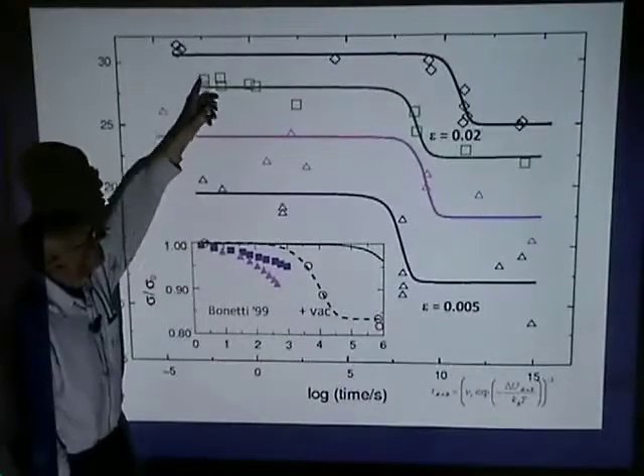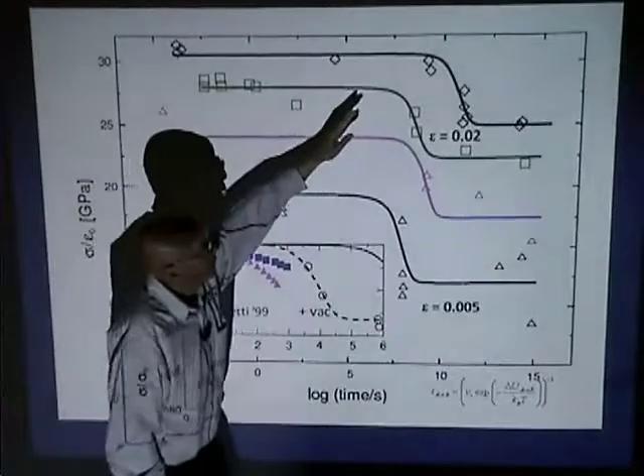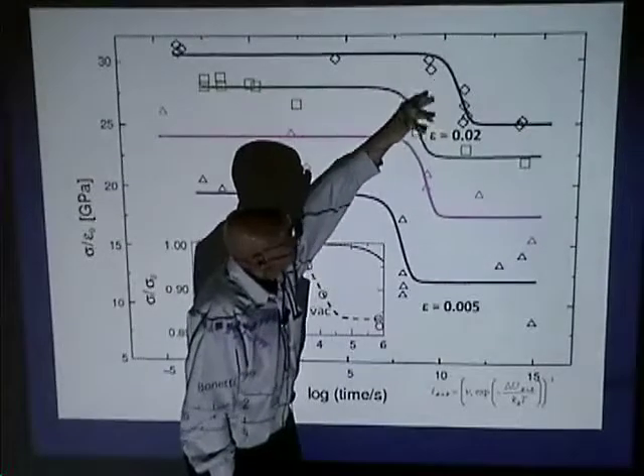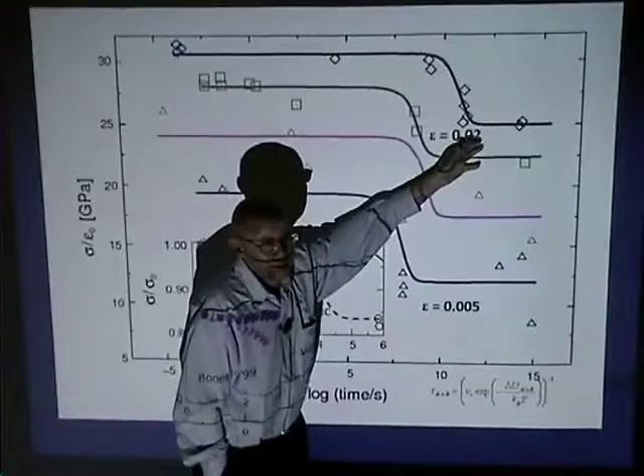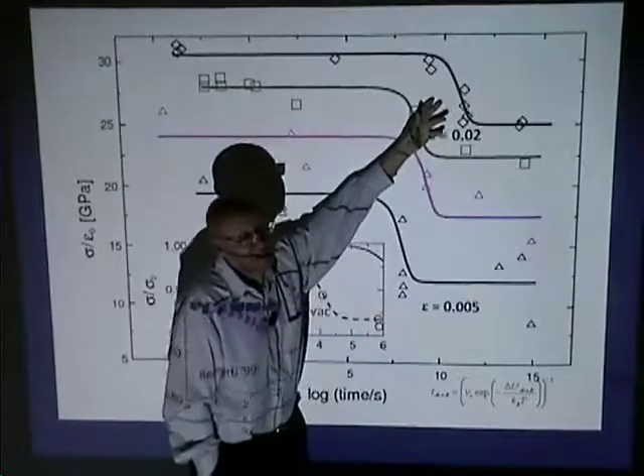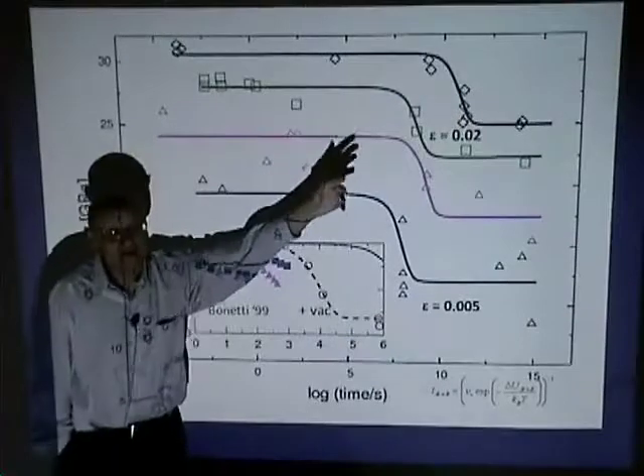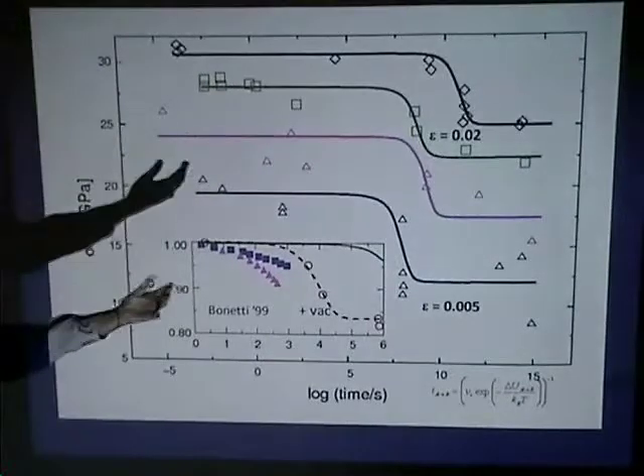What you see is that the system takes a very long time before it starts to relax, and then it undergoes relaxation from some initial stress to some final stress. We even tried fitting this not to a single exponential but to a stretched exponential, and guess what beta is? 0.7. No big surprise, so it's almost like an alpha relaxation.